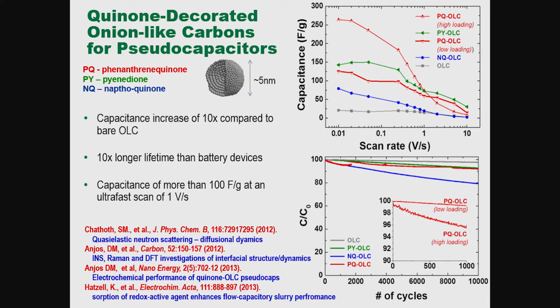What is the payoff for that? For instance, we had done studies of the adsorption of a variety of quinones on onion-like carbon surfaces, which are inherently defective, and we see very nice capacitive performance, particularly at lower scan rates, pseudocapacitive behavior.